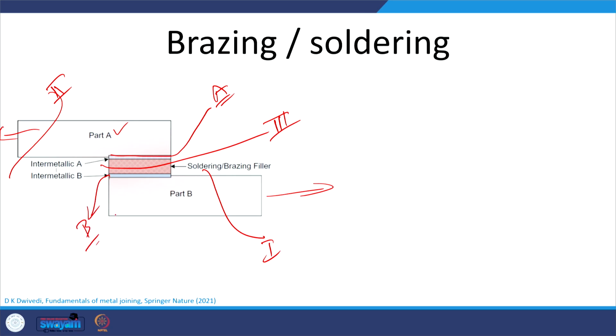Okay. So, we know that the joint is just like a chain. Whenever load is applied, the weak link will fail. So, which is the weak link that will trigger the fracture. Okay. So, say when the load is being applied, failure can occur from the parent metal B, or failure can occur from the parent metal A, failure can occur from the soldering material or brazing filler, or failure can also occur from the interface of the filler with the part A or interface of the filler with the part B. Whichever is the weak, that will fail.